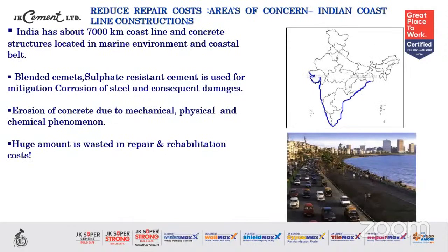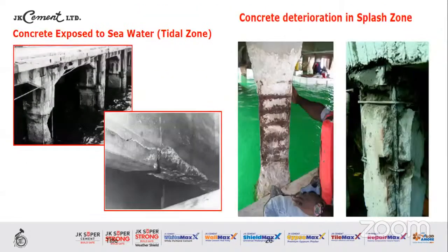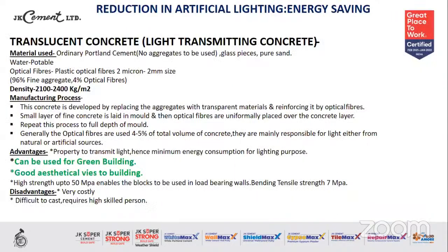For the coastal regions also, where the susceptibility of concrete to chlorides and sulfates is very, very high, Portland slag cement or Portland Pozzolana cement is going to be the proper reply to combat the issues of longevity and durability of such concretes. Such hazards and structural damages can very well be avoided if we use blended cement in coastal regions.